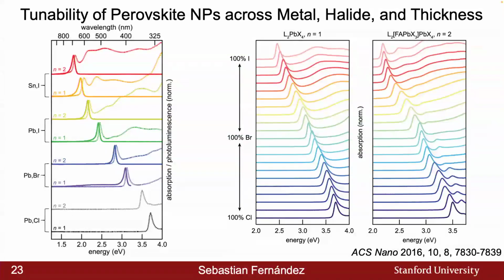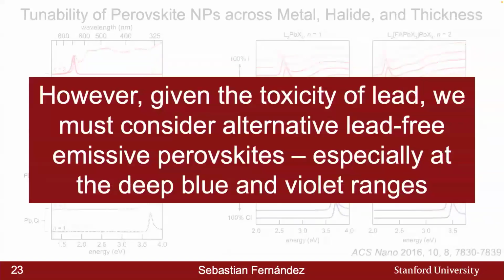And so where do we move on from here? Well, we can see that the tin-based system offers a lead-free and hopefully reduced-toxicity or toxicity-free platform for these materials. And from my own previous work, and those before me from the Congreve group, it's been shown that there's a pathway to use manganese dopants, and hopefully a full manganese platform at some point, to reduce the amount of toxicity for the green, red, and sky blue regimes of the visible spectrum. But we're missing a solution here at the deep blue and violet range.